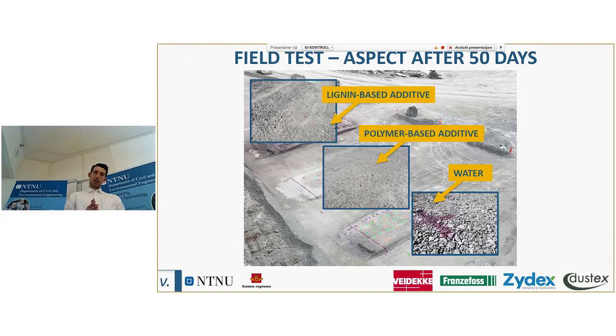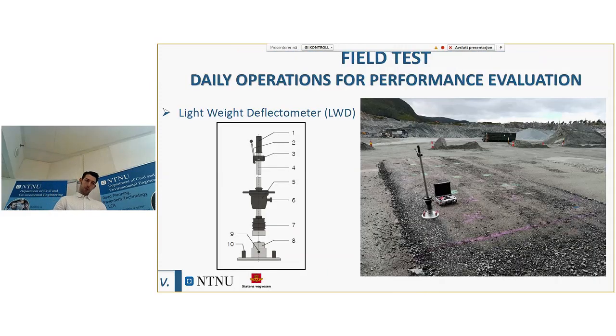This is the aspect after 50 days. Of course, we can see that in the water-only area, the rocks are still there, unbounded materials. But when it comes to the polymer-based additive and the lignin-based additive, we can see just from sight that there is a binding action. But of course, we need to assess the results from a scientific point of view, from an objective point of view.